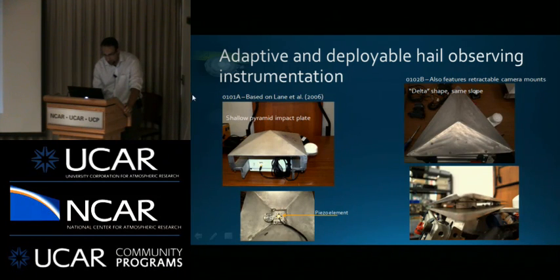So following the Lane paper, you have a square weld at the apex of the pyramid with the piezo mount. We also notice if you try to use adhesive, you will definitely cause a voltage signal that can bias your information if you actually put an adhesive on the piezo. So we actually use very, very tiny set screws that are off the ceramic portion of the disc, and they're all uniformly torqued to hold that piezo, so we don't try to bend it and induce a voltage bias there. And the same applies to the delta shape after we decided to go away from a piezo on each face.